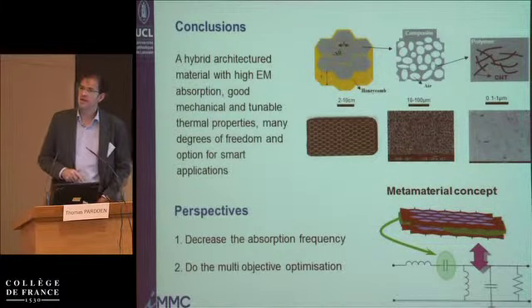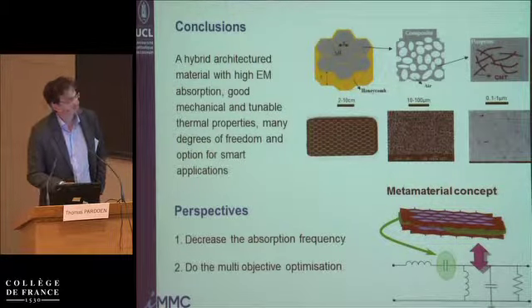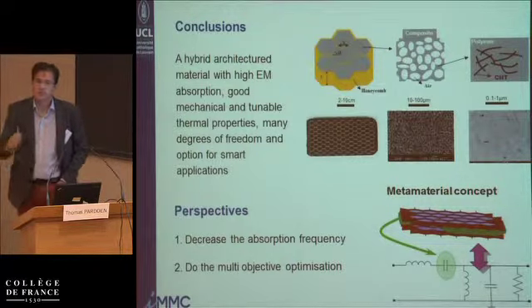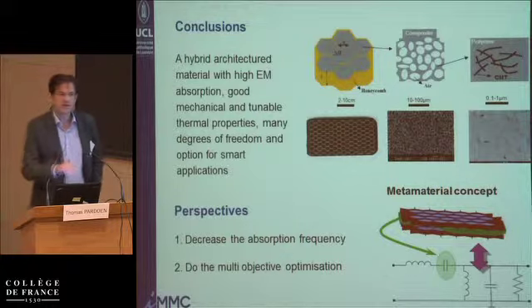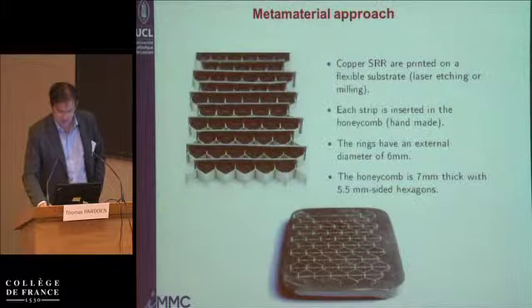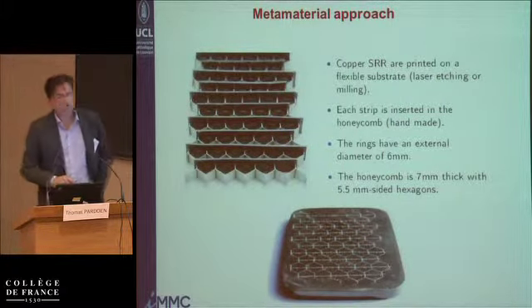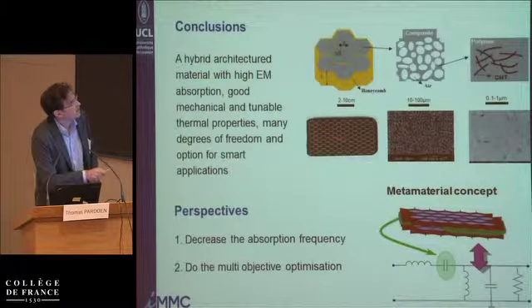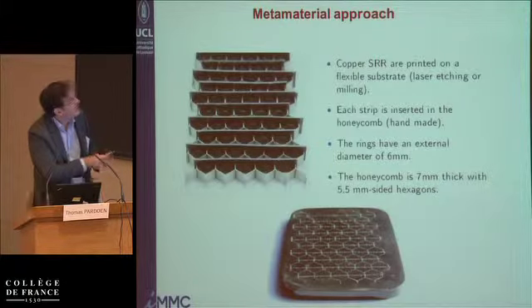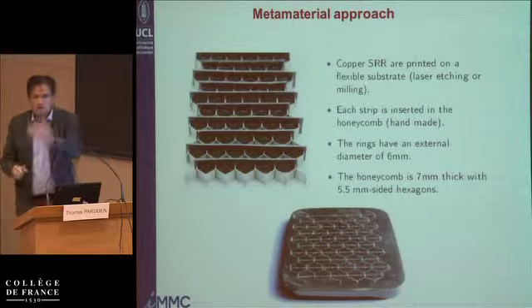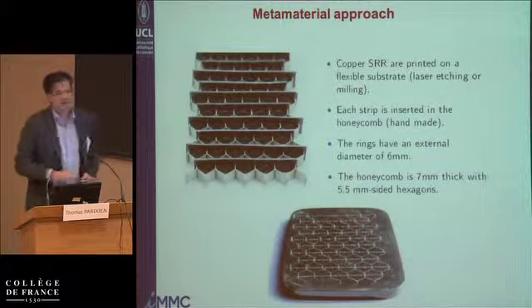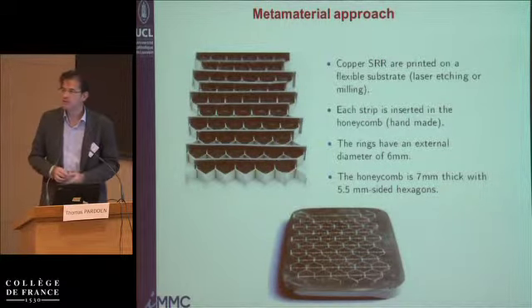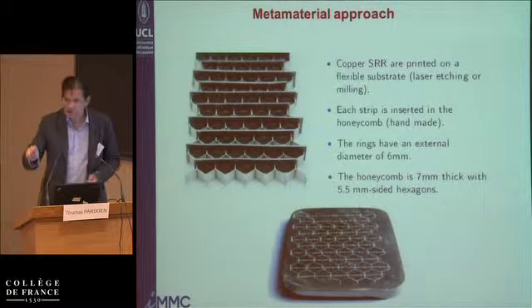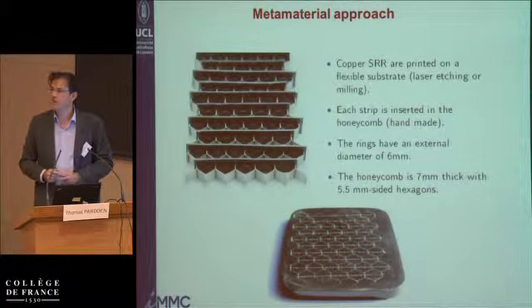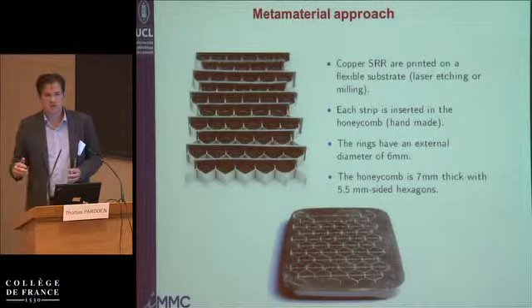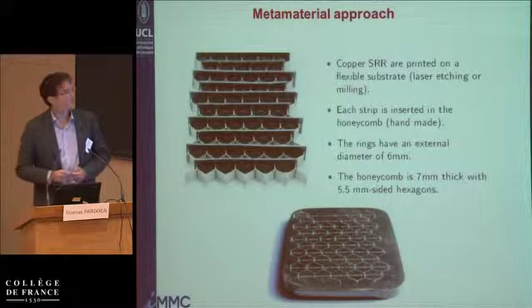There are some applications where it would be nice to absorb below, and Pierre is working, and this is the end of his thesis, on a metamaterial approach where we develop a concept where you can have a dielectric constant below 1 and permeability which is below 1. I think my time is reached, so I'm just showing you this image of what Pierre has recently performed. On top of all the material here, he is also introducing some thin copper rings inside the honeycomb, and there will be the foam around. This ring is adding an extra capacity into the system and transforms the material into a metamaterial. By doing that, he is able to get an absorption peak below the cutoff frequency that we have. So it's not as good as what we have above 2 gigahertz, but it opens some avenues to also absorb below the 2-3 gigahertz range.